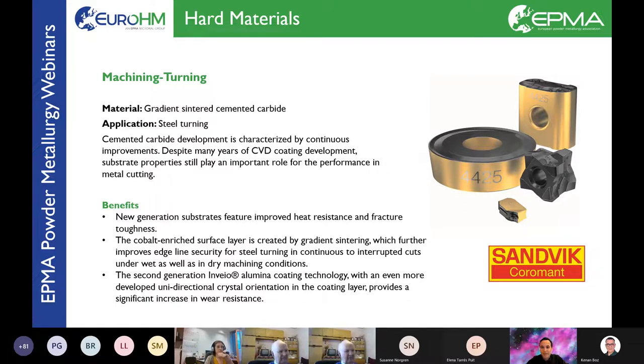So we are creating this type of microstructure by making a proper selection of powder, of sintering process, and also on how to play around the different components to create this modified surface used in this particular case. And then, of course, as it was mentioned also in the presentation, we usually are coating these carbides, and in this case, it is the chemical vapor deposition, the multi-layer providing the needed properties in the machining. So the combination of the carbide and the coating is giving these unique properties.